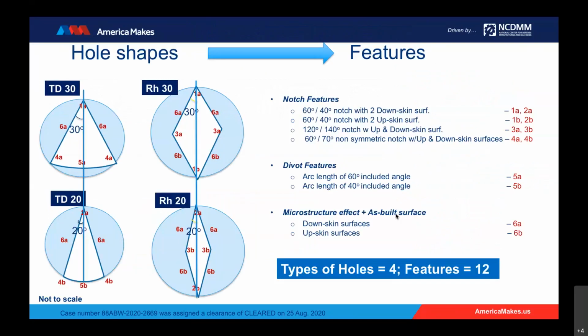One of the challenges here was, how do you quantify this whole geometry in a model? To do that, we've further broken down this whole shape into basis features, which primarily comprise notches, divots, and microstructure or skin effects. If you were to take the rhombus hole, you basically have 4 notches. So we sampled tensile coupons with these notches in the gauge volume, so we could assess the influence of the presence of this notch on performance.